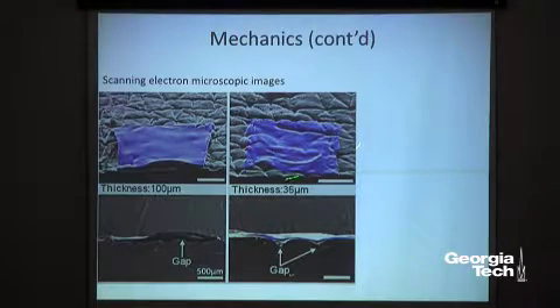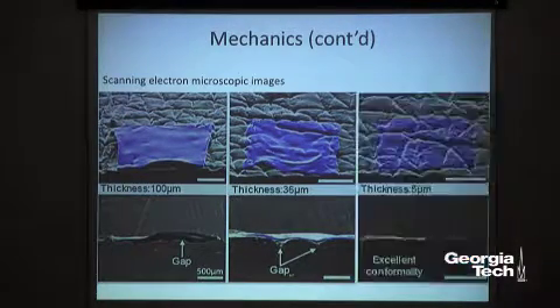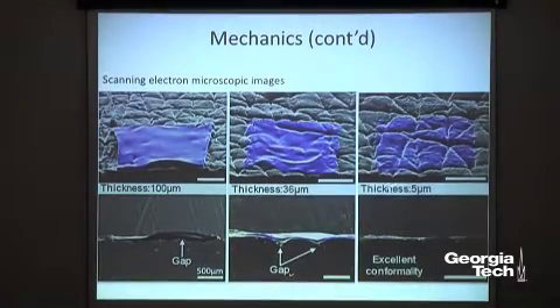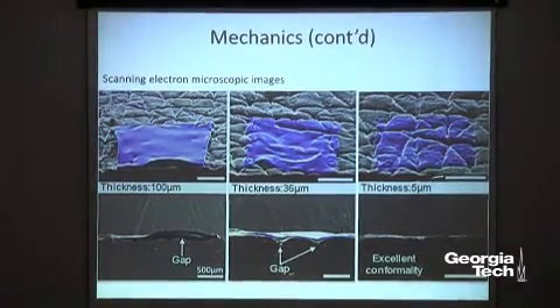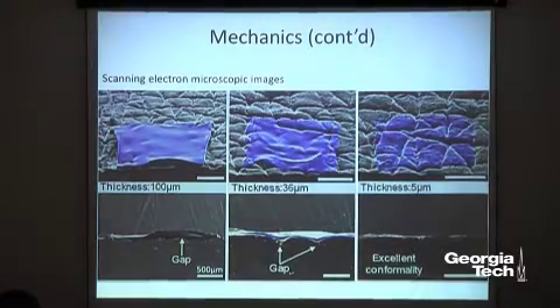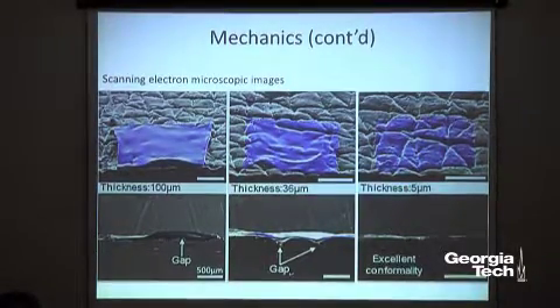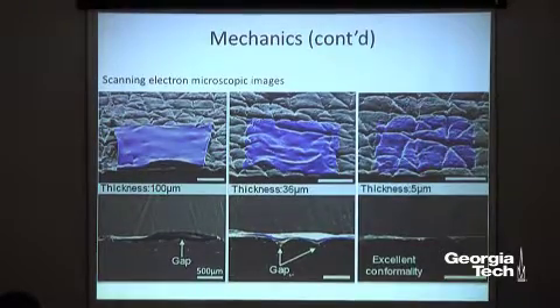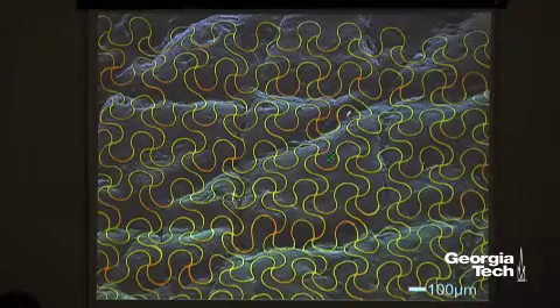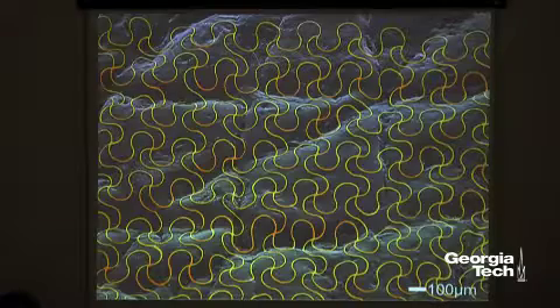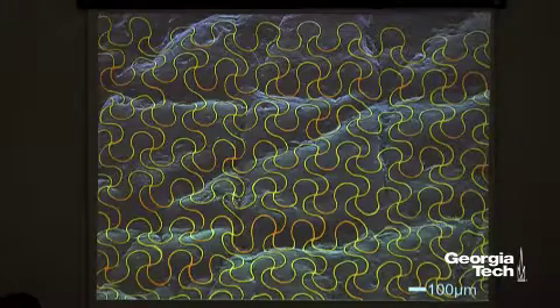So now about 35 micrometers, you see that looks a lot better compared to this guy, but still we have gaps. So I reduce further and further. So now 5 micrometer thick membrane. As you see, it has pretty nice conformal contact to the skin surface. If you zoom in, now you see this nice gold electrode is following the background, which is the skin.